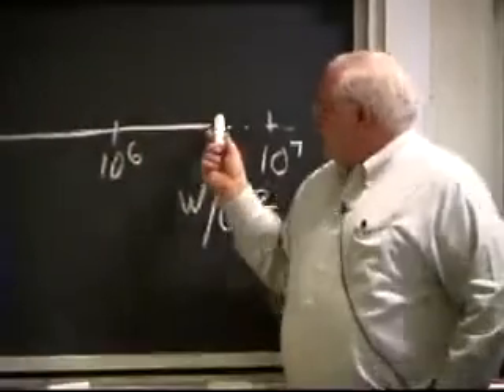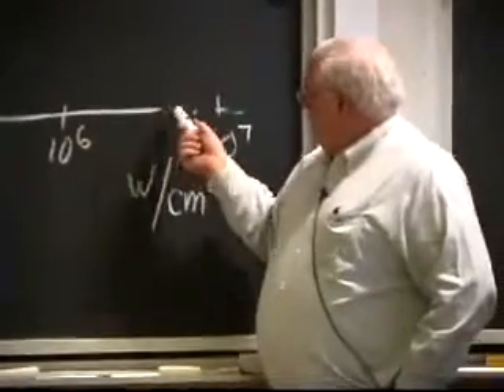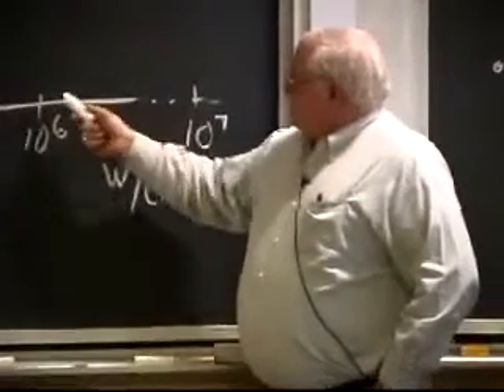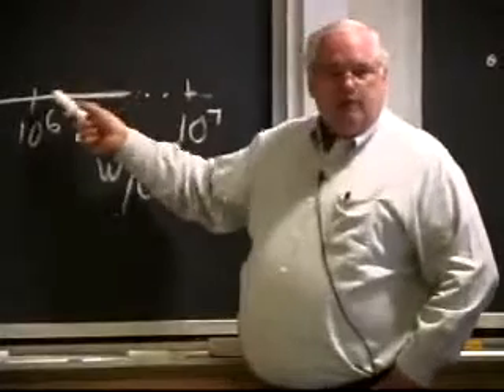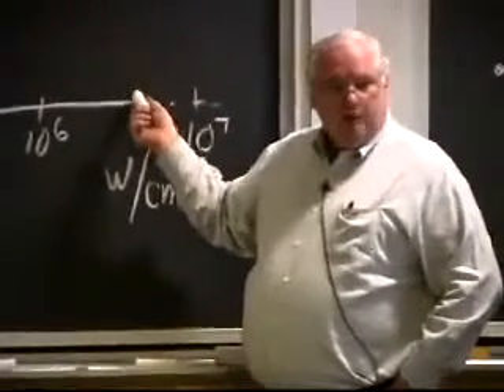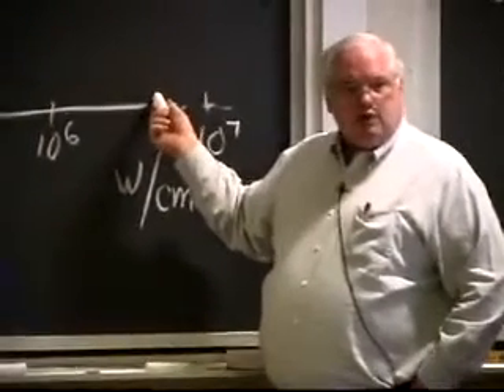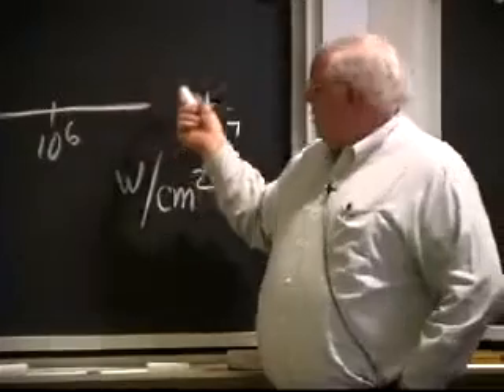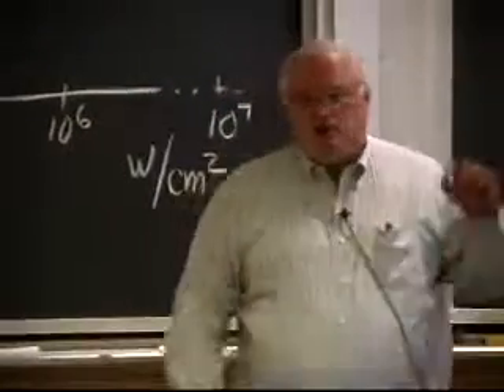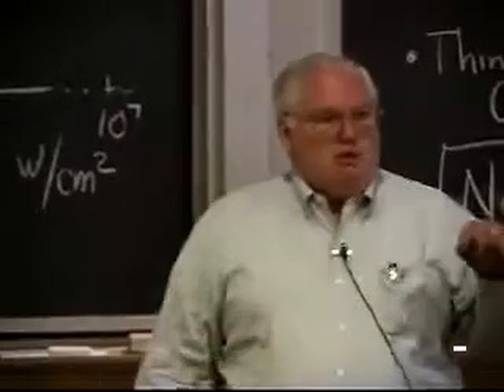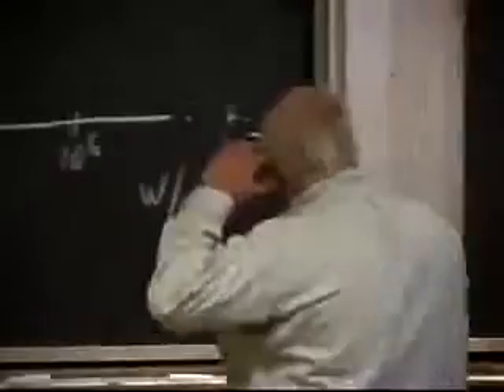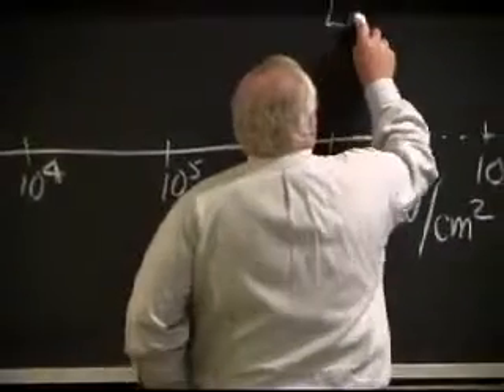You start vaporizing the metal, certainly at 10 to the 7th, and I've started dotting these things. Depending on the thermal conductivity of the metal you've got, if you've got aluminum and copper, you may be able to go to 3 times 10 to the 6th and still produce a weld. You go to 10 to the 7th or 10 to the 8th, and you start laser or electron beam hole drilling. And it turns out lasers and electron beams are up in this range.